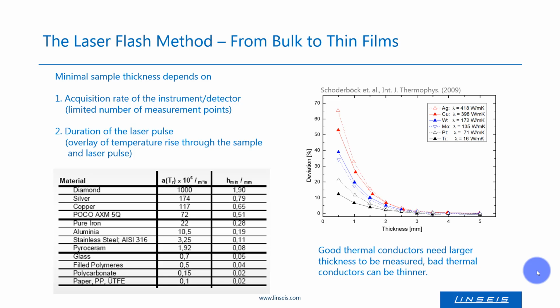This experimental setup works well as long as the timescale for the measurement is not too short. But the higher the thermal diffusivity of the sample is, and the thinner the samples get, the bigger the measurement error gets. You can see an illustration of this correlation in the graph on the right side, published by Schoderbock et al..